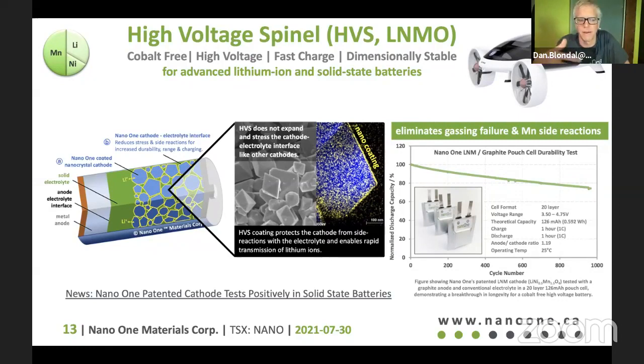They either develop a whole bunch of gas and puff out, or the manganese dissolves and fouls up the graphite anode, and they only last a couple cycles or a dozen cycles. We found a way to protect this material and work with the right combination of electrolytes to make this last out to 1,000 cycles. This is a very remarkable achievement, and certainly draws a lot of attention in the industry, and it's resulted in us having many different test programs underway to evaluate this material. It should be very effective in power tools, high power applications, and ultimately the electric vehicle space as well.